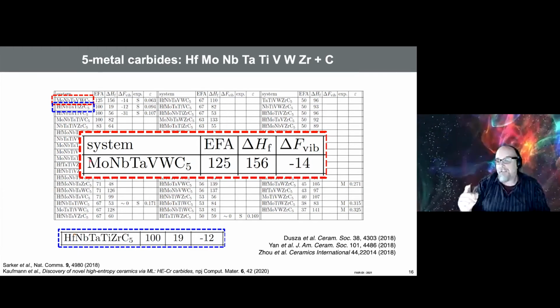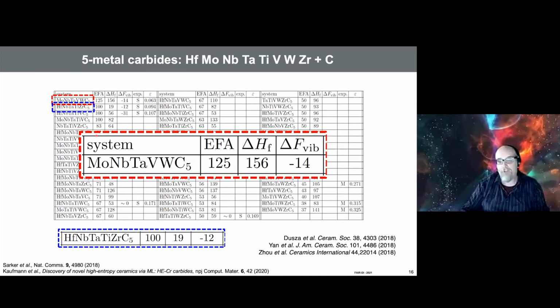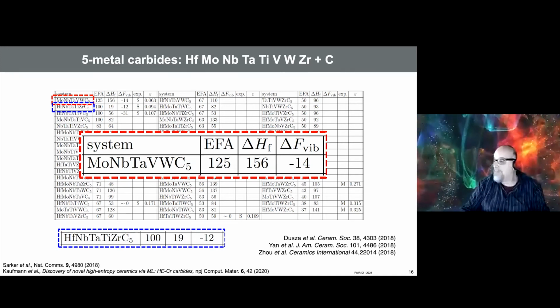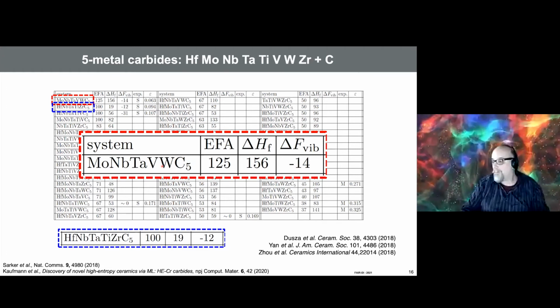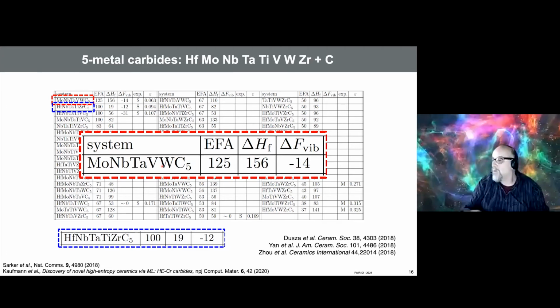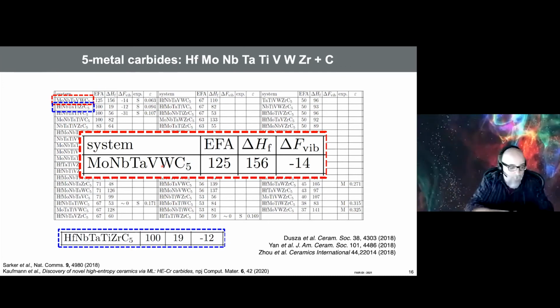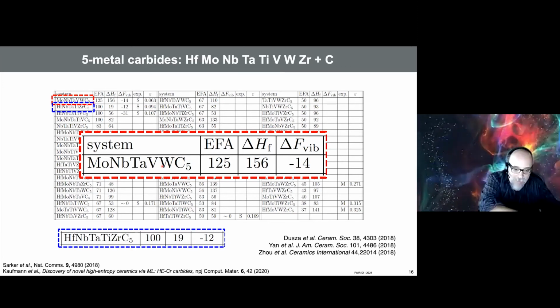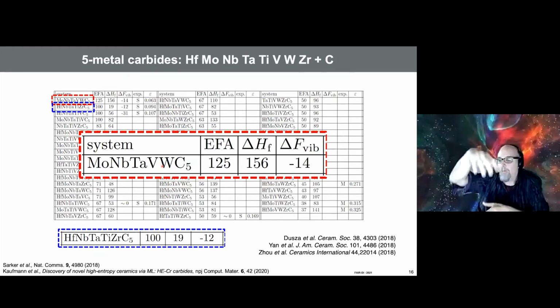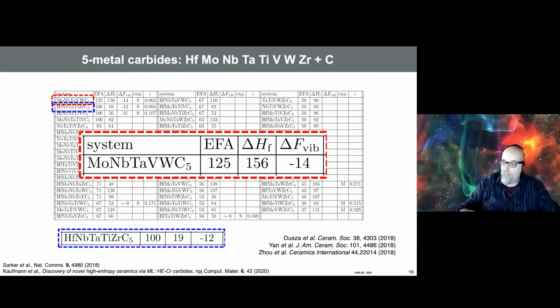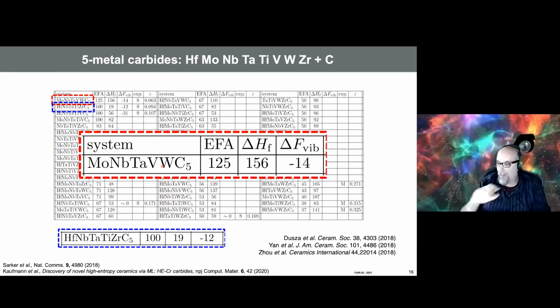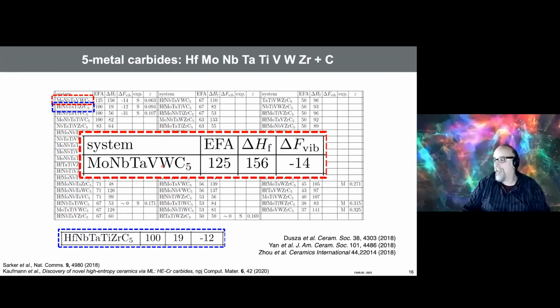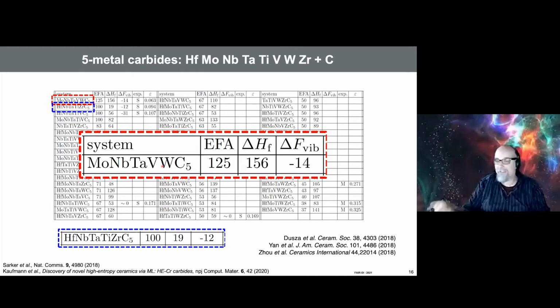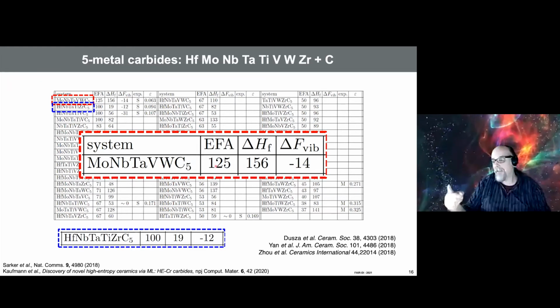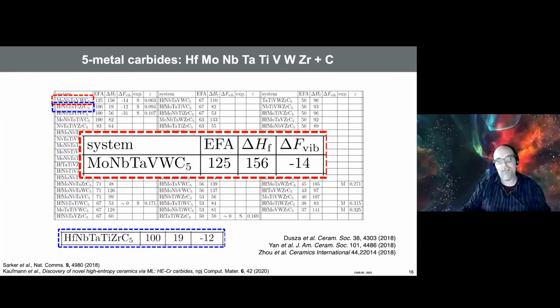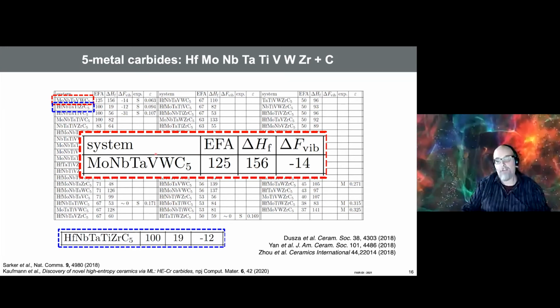Fine. But the success of big data is actually the first, because both molybdenum carbide and tungsten carbide are not cubic. One is rhombohedral and the other is orthorhombic. So practically you're mixing 3 cubes plus a bunch of hexagons, plus a bunch of orthorhombic things that are like elongated parallelepipeds. You don't expect to get a rock salt, but still you get it. And this was completely unexpected. And this is really a success of this big data analysis that led to other research.